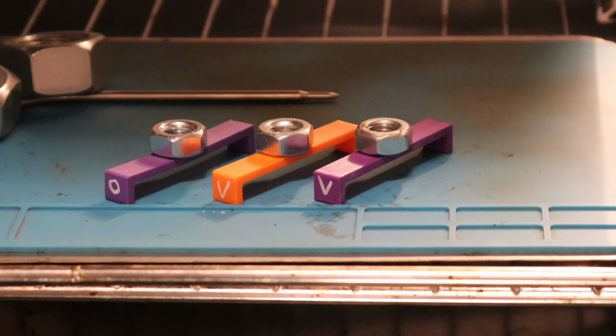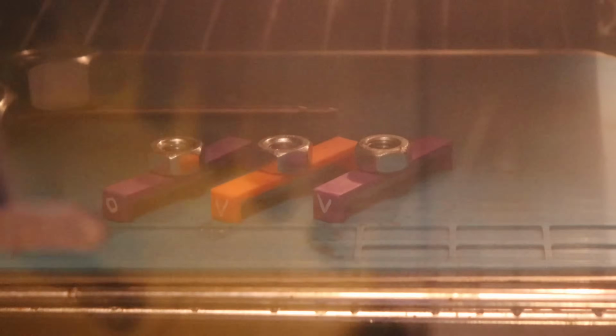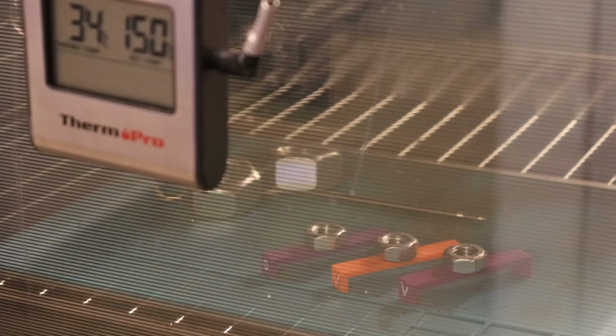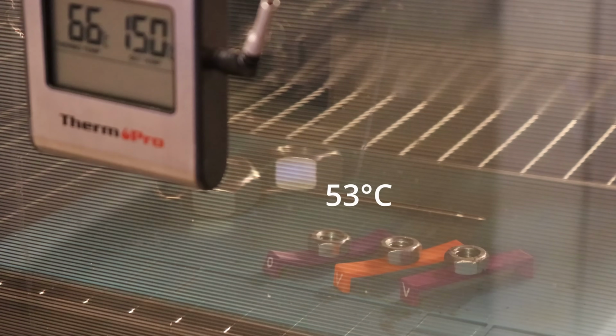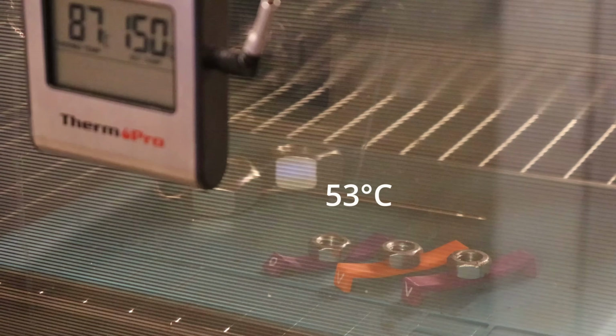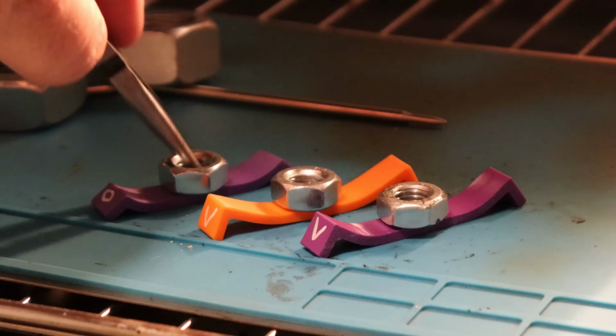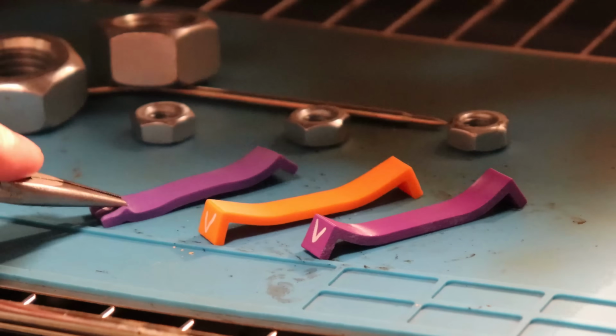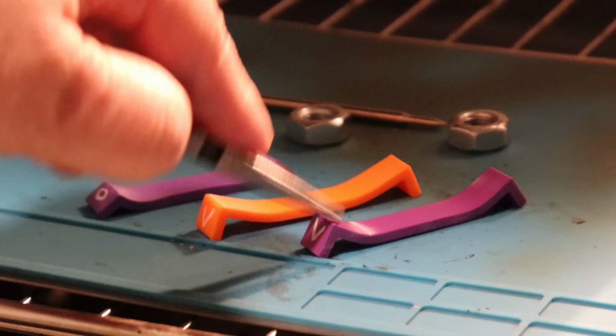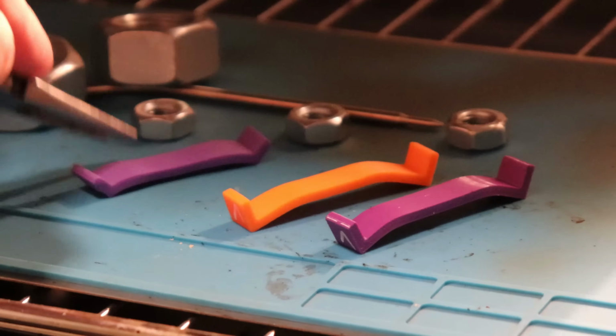Temperature test in the oven, and this one is the Overture PLA. I want to record the temperature of the first deformation. And no surprises here, approximately at 53 degrees Celsius it started with deformation, which is typical for most PLA filaments. But I also noticed visually it has more shrinking compared to the ordinary PLA materials.